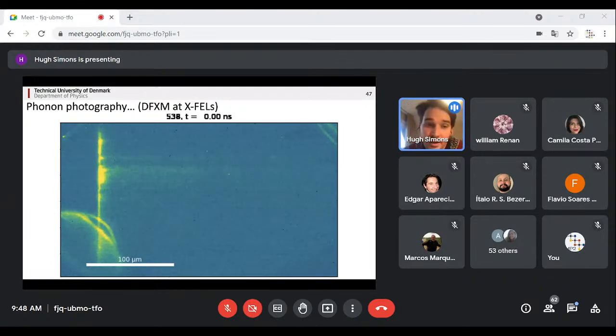And this, I think, is super exciting. I've spent my education reading about what phonons do and why phonon scattering is important, but to me, they were always kind of an abstract concept in solid state physics textbooks. But now we actually have the ability to visualize acoustic phonons inside materials almost in real time, actually. So this is just a test case, but we're really excited to be moving forward with this and measuring not just idealized acoustic phonons moving through materials like diamond, but actually watching how they, for example, interact with defects like dislocations and grain boundaries and domain walls, and how they give rise to phase transitions. So this is something we're working on at the moment, and we're very excited about.